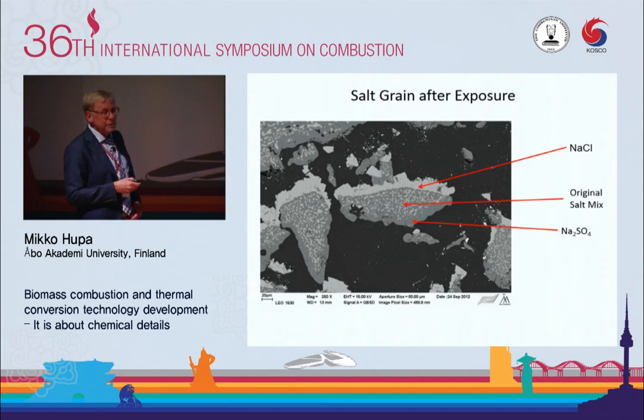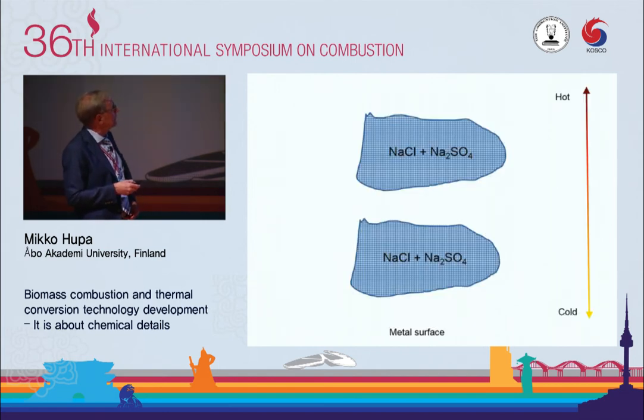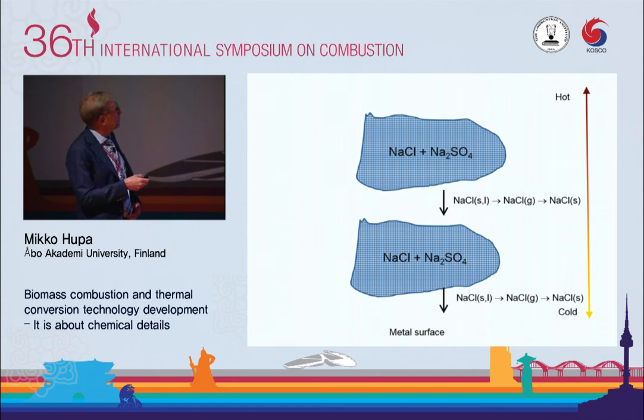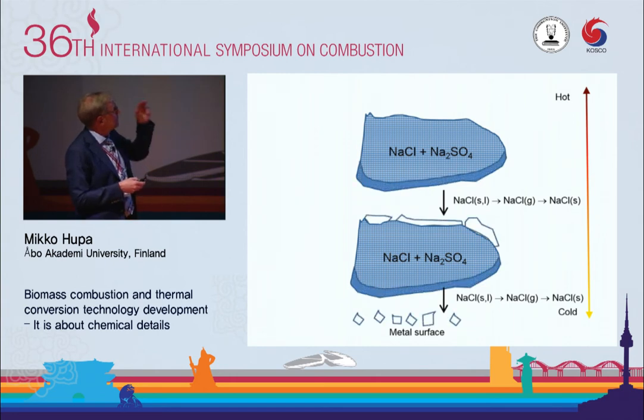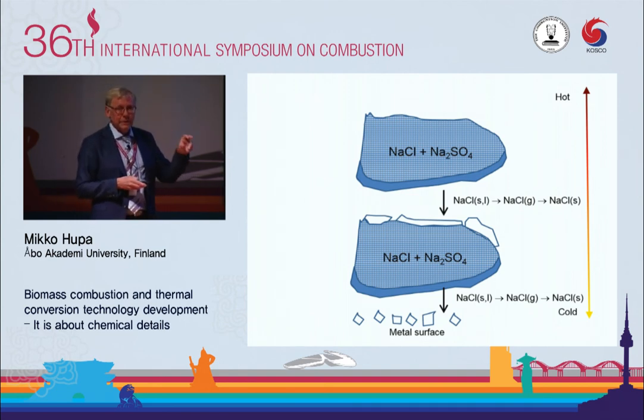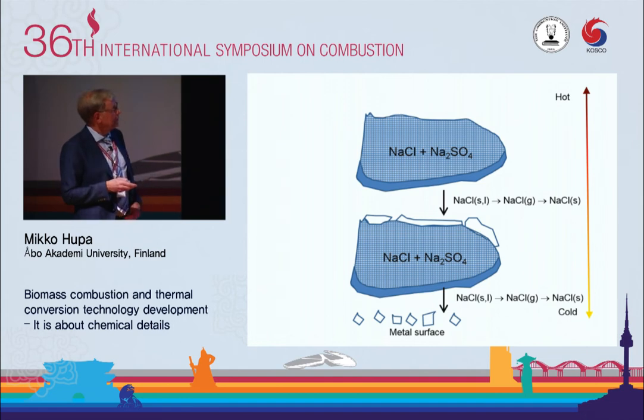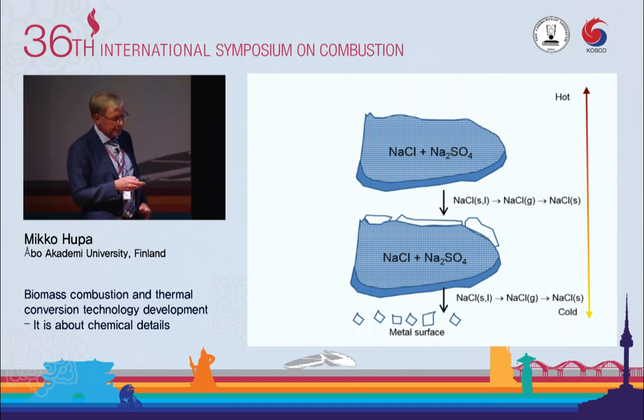And now today, we think that we understand that quite well. So if the cold is down, hot is up, this is the way it goes. So simply sodium chloride starts vaporizing and is removed from the lower parts of the particles, and then it hits the next particle. And the interesting thing is that the driving force here is an extremely small temperature difference. These are small particles, 100 micrometers, but it's sufficient to transport material.